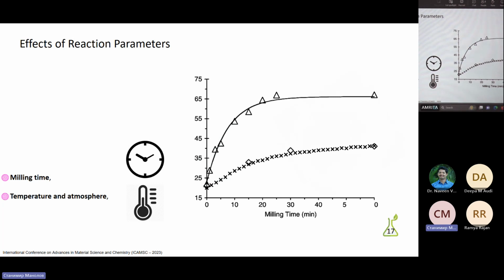The milling time has increased the yield of the reaction because the collision numbers and the total amounts of transferred energy have also increased. In some cases, the product can be decomposed due to the increment of contamination and the formation of undesirable phases with long milling time. The milling time has also changed the morphology and mechanical properties of the product.